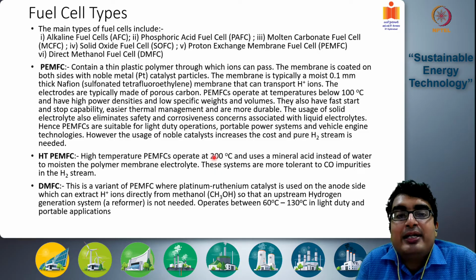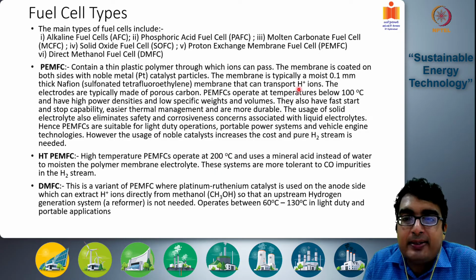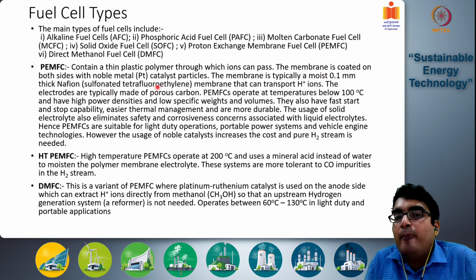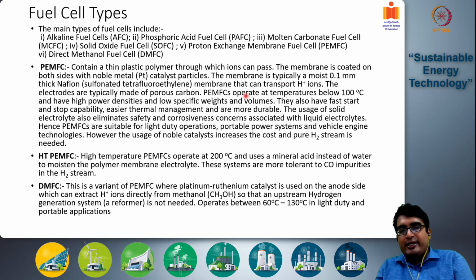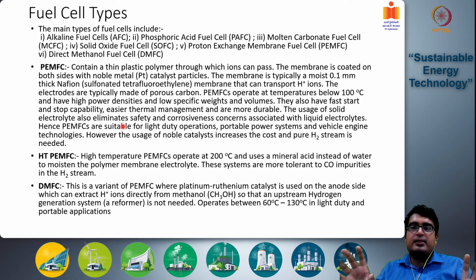So this PEM fuel cell, the reverse of the PEM electrolyzer system, contains a thin plastic polymer through which ions can pass. The membrane is coated on both sides with noble metal platinum catalyst particles. So this uses platinum catalysts. The membrane is typically a moist 0.1 millimeter thick Nafion, sulfonated tetrafluoroethylene membrane, as we discussed, that can transport H+ ions. The electrodes are typically made of porous carbon, coated with the platinum catalyst, which helps in the reaction processes, and the intermediate electrolyte is a polymer exchange membrane, Nafion, which can transport H+ ions.